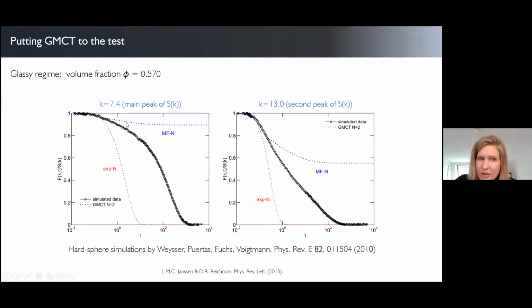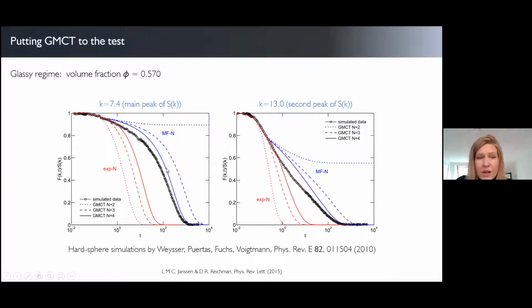This is where standard mode coupling theory breaks down completely because it predicts a glass here, while in reality, the system is still on the liquid side of the transition. And going one order higher in generalized mode coupling theory actually brings us much, much closer to the result that it should be, and the highest order gets even closer. So there are two things I want to point out from these results. First of all, note the uniform convergence pattern. Each higher level in the GMCT hierarchy brings us closer to the simulation data. And so that's encouraging because it suggests that we don't necessarily have to go to infinite order to already get a good estimate of the infinite order solution.